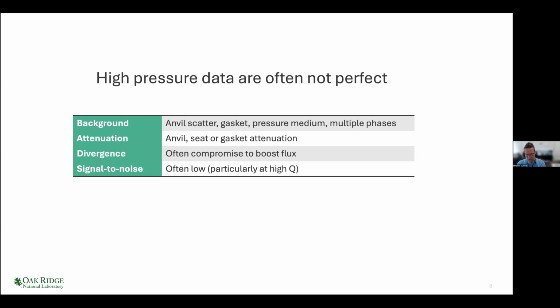And then, of course, to make things interesting, the data themselves are not perfect normally when you measure at high pressure. So we have these main issues, background. So that could be either scatter from the anvil, scatter from the gasket. There's normally a pressure medium in there, which will also scatter. And very commonly, we'll have multiple phases as we use pressure to explore phase transitions. There'll be attenuation going on. So the anvil can attenuate the seat, the gasket.